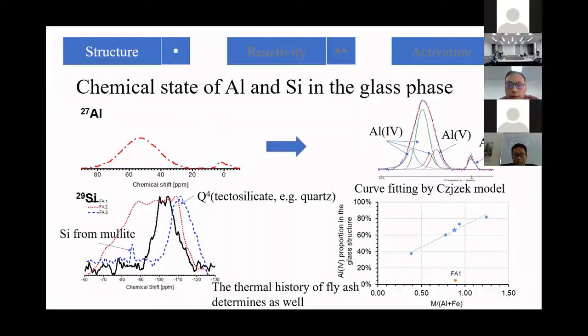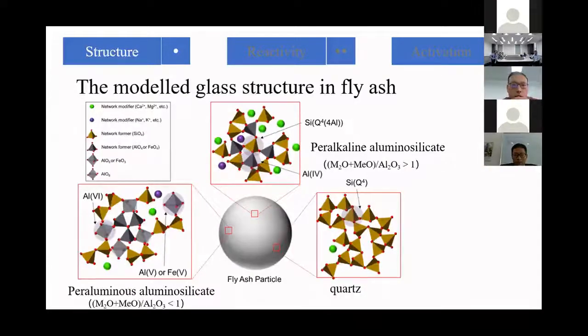It's 6 coordinated, and from the ratio between the alkali cations and the aluminum and iron contents, we could also speculate on the proportion of 4 coordinated aluminum in the glass structure. Also from the silicon stage, we could see the silicon from mullite and the silicon from tectosilicate, either from the crystalline phase like quartz or from the glassy phase. Based on these chemical environments, we could give a model to describe the glass structure of this fly ash.